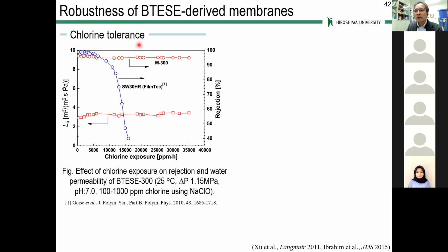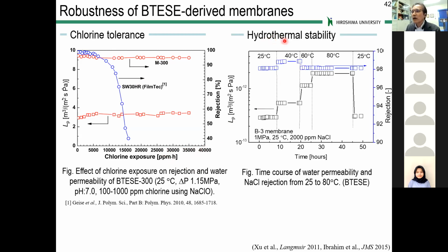And these membranes were evaluated for robustness. This indicates chlorine tolerance. Okay. Now the rejection of BTESE derived membranes and also the rejection of SW30HR are plotted as a function of chlorine exposure, in ppm hours. After contact with chlorine, the SW30 shows decreased rejection. This indicates degradation occurs in the case of the SW30 membranes, while our membrane stays stable even after contact with 35,000 ppm hours. The right side indicates the hydrothermal stability of our BTESE membranes.